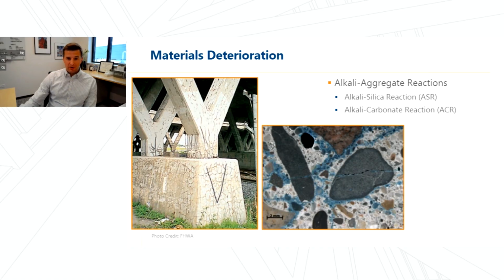Moving to the last chemical reaction that we'll talk about, alkali aggregate reactions. It comes in a couple different forms, but ASR, or alkali silica reaction, is most common when we have silica-containing aggregates like chert. But in both cases, this is generically a chemical reaction between the alkaline environment, that high pH environment of concrete, and reactive aggregates. And this again can result in expansive gel that can cause cracking and loss of strength. But it's important to note here that the reaction rate and severity can vary. Not all reactive aggregates and not all environments exposing reactive aggregates will cause deleterious damage.